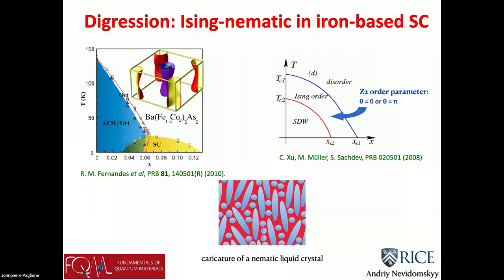But prior to doing this, you could have a disordered state that nevertheless has this Ising order parameter that's been broken. Yes, just one small correction. It was originally suggested to be an implementation of the Coleman-Larkin paper with order from disorder. Later, we realized that there is already, on the mean field level, strong biquadratic coupling related to degeneracy, which does its job much better. Yes, it doesn't change anything on a conceptual level, but it's not order from disorder.